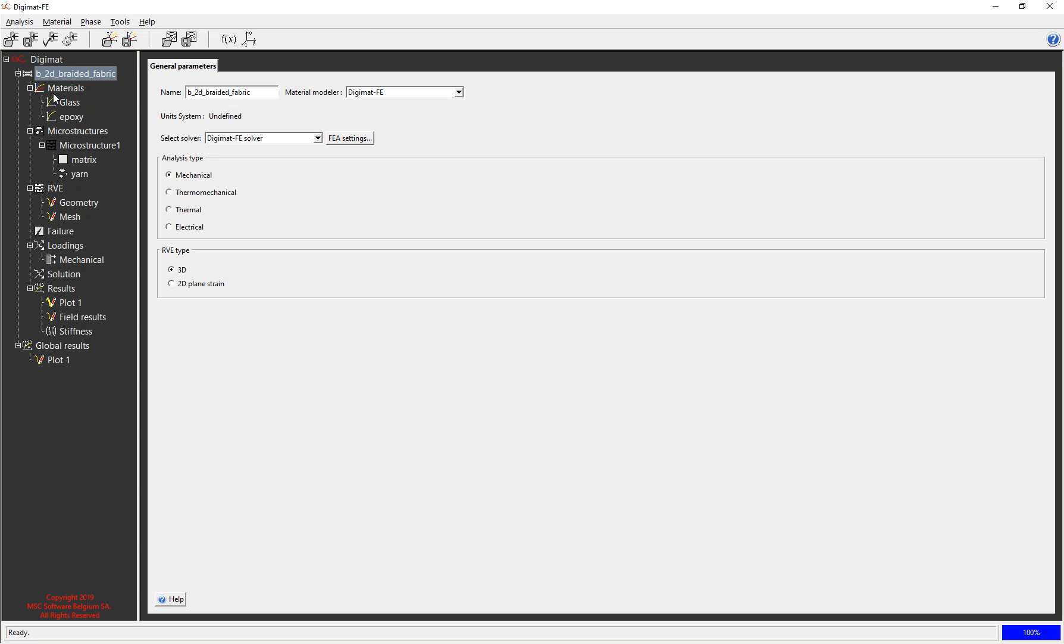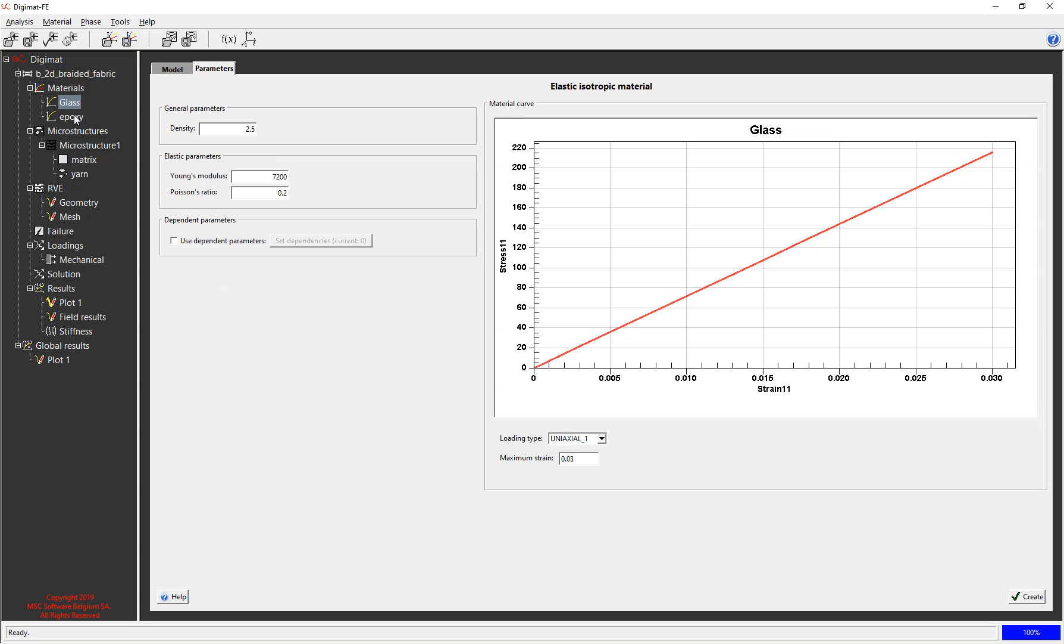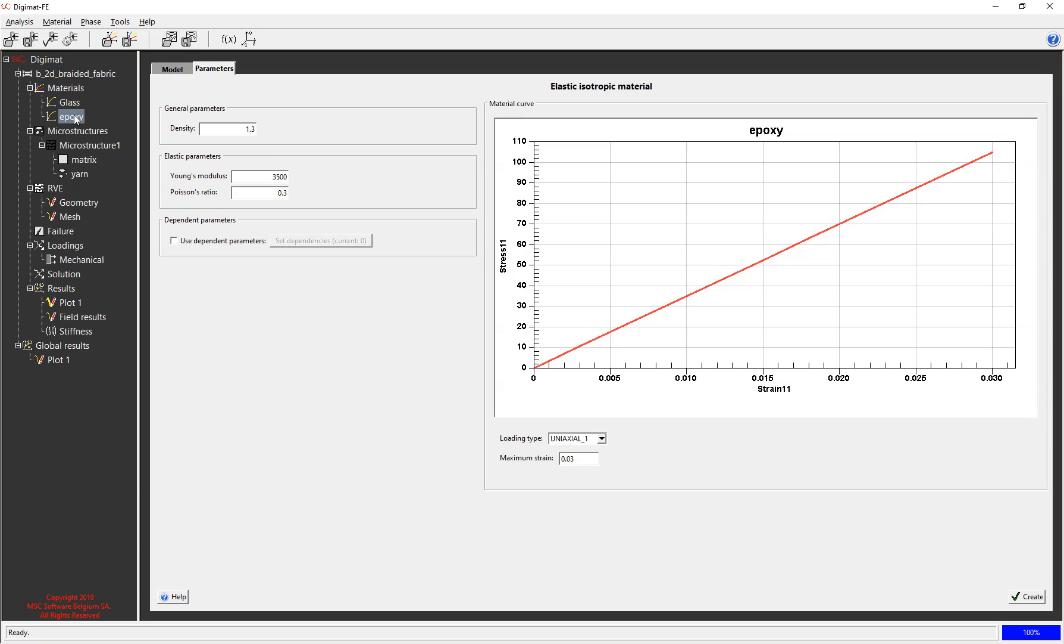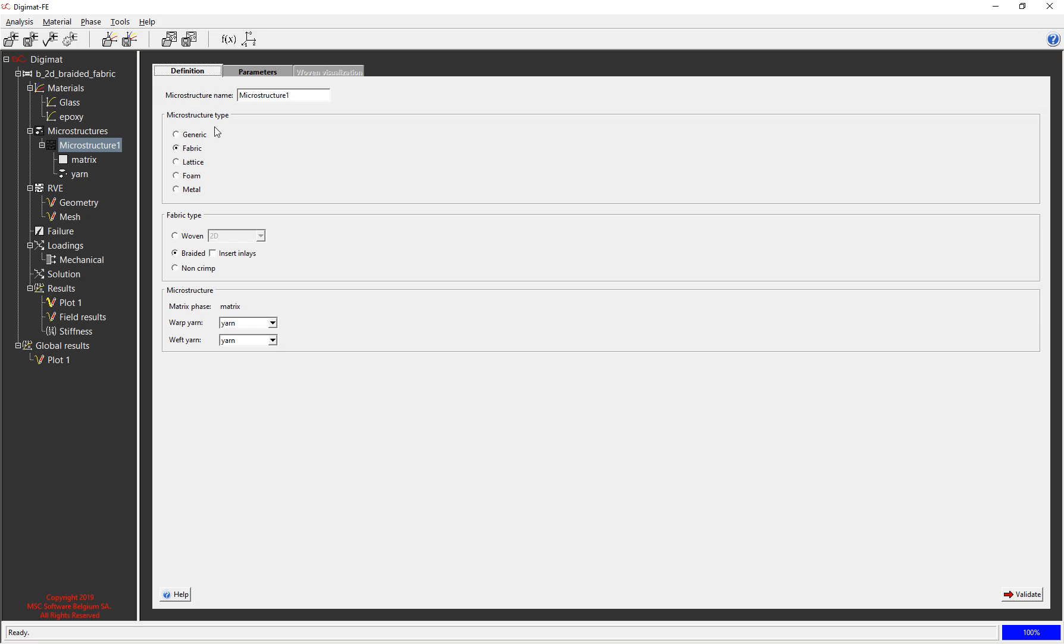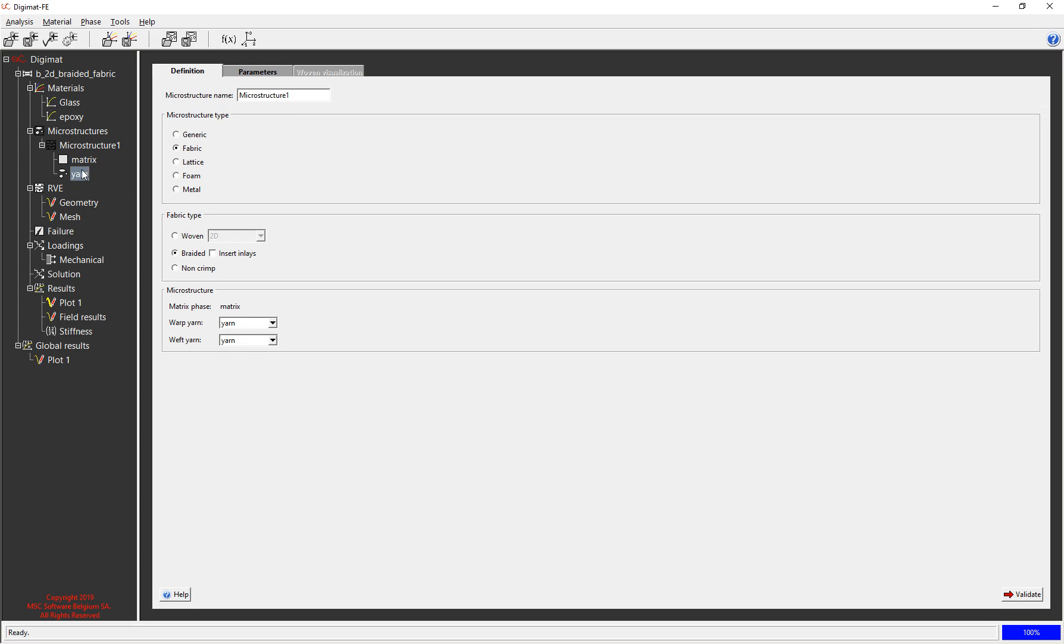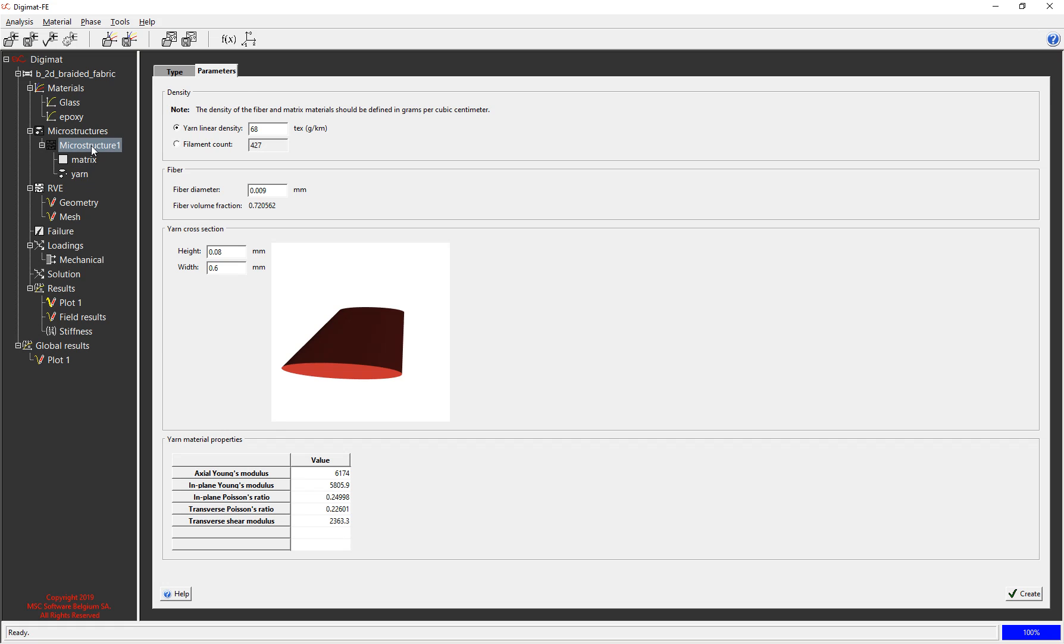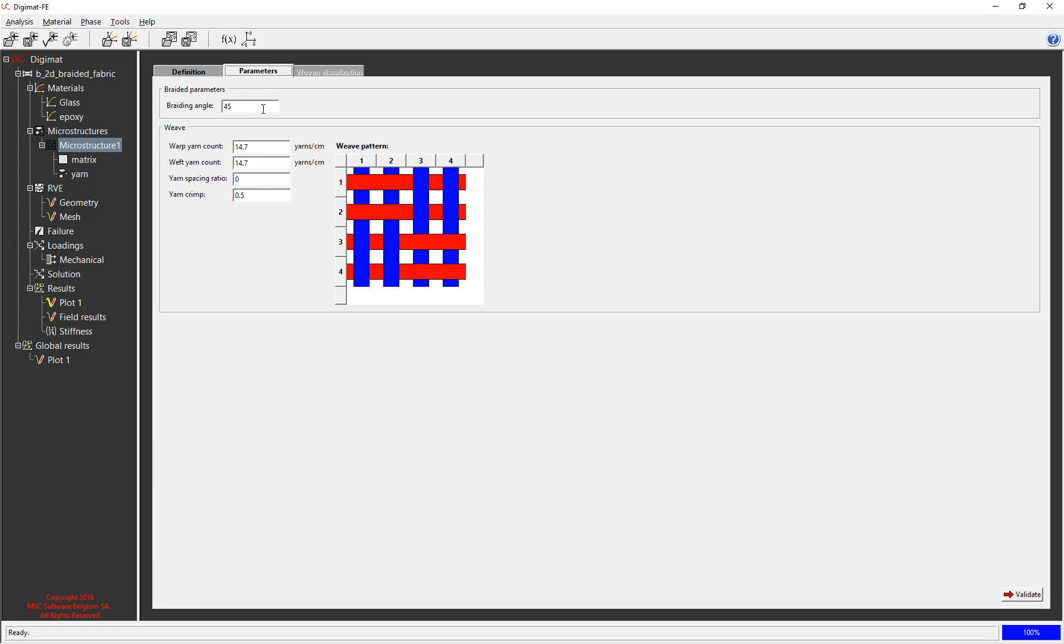So obviously the GUI is basically identical and we add an analysis and we work our way down here. So I define the glass and the epoxy in exactly the same way. My microstructure in this instance, what I can do, you're basically defining a fabric where you choose the matrix and the yarn. So you can have different yarns in different directions. Your yarns are defined in terms of linear density and the cross-sectional dimensions and the individual fibre dimensions here. So back in the microstructure, we can define the braiding angle, the count and then we can play around with the weave pattern to decide how this thing is woven together.